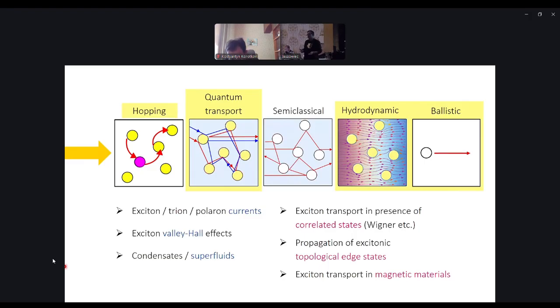If you have high mobility, then of course you can apply an external field and have drift currents over microns, but there too, the moment the exciton encounters non-radiative states, that will limit the transport. And maybe the last part: if we have a bright exciton state, which recombines very quickly, this would be a problem to begin with, because we'll have a natural recombination channel. So if you want long-range transport, we're better off looking for a dark state, an exciton that does not emit light very quickly. Yeah. All right.